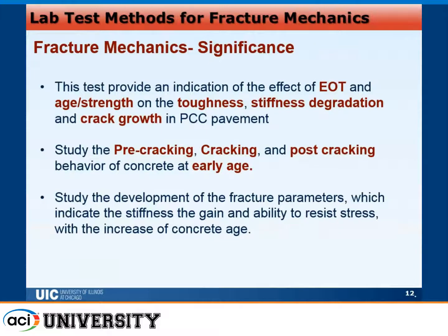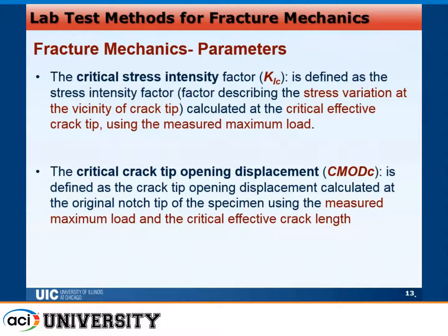The significance of fracture mechanics is to provide an indication of the effect of early opening to traffic and age on the toughness and stiffness degradation and crack growth in PCC pavement. We also need to study the pre-cracking, cracking, and post-cracking behavior due to the tension softening curves after performing the load CMOD curves. The parameters to be investigated are the stress intensity factor, which is an indication of the stress variation in the vicinity of the crack tip, and the critical crack mouth opening displacement, the CMOD, defined as the crack tip opening displacement at the original notch tip.